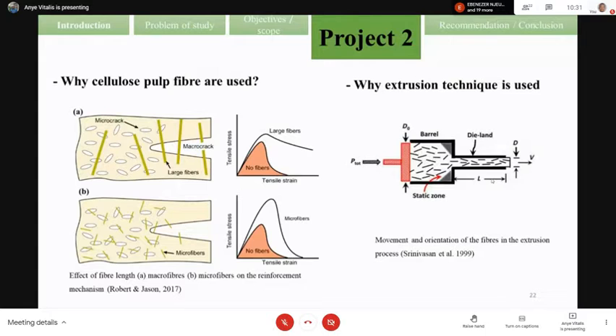So why are we using cellulose fiber in this study? Cellulose fiber, because it has a micro size, will help us to bridge the cracks. You will have a significant bridging at the micro scale. By bridging that, it will help us to inhibit crack propagation in the pores, at the micro scale. Also, you increase the tensile strength and also the toughness of our material.